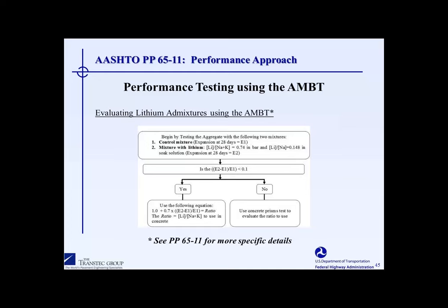Without going into detail in it, one point is certainly worth making, and that is, based on a significant amount of data, there will be certain aggregates for which you could not use the accelerated mortar bar test to evaluate lithium. That's one of the first steps of our protocol for testing lithium: you run a quick screening test, and the outcome of that may in fact point you down here to the bottom right-hand corner, telling you that you could not use the results from the mortar bar test, but rather you must use the concrete prism test.